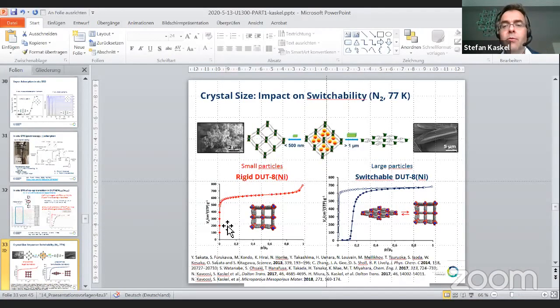And the adsorption enthalpies for the rigid variant are very similar to normal MOFs, so between 10 and 40 kilojoule per mole. Exothermic, of course. But what we have to say is that the structural transformation requires also a heat of transformation. And the adsorption enthalpy has to compensate that transformation energy that is required. Therefore, when you measure the heat of adsorption at the step where the transformation happens, you will see that the heat of adsorption and the heat of transformation start to balance each other. So they come to a point where they are closer to zero, let's say it like this.